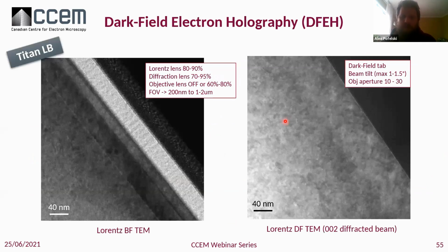So going through relatively quickly, this is first an image in Lorentz bright field TEM. So typical settings that you will have here: relatively high excitation of the Lorentz lens, relatively high excitation of the diffraction lens. The objective lens is either turned off, or you can slightly excite it. This is what we call the dual lens mode. It's kind of a complicated way, but that is helping in adjusting the field of view. And the typical field of view you get is from 200 nm to 1 micron.